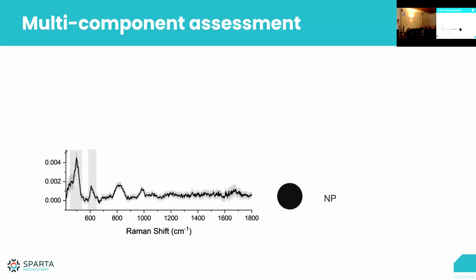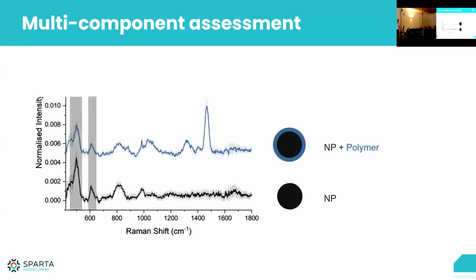So we have the bare nanoparticles, and you can see different marker peaks that we can draw down here. And then we're adding a polymer on the surface. And you can see we still have that same core composition, but a bunch of extra peaks come up from the polymer that we coated on the surface of these particles. And again, we could look at the variation in that polymer coating as well. This was super homogeneous, which you can see from this average plus the standard deviation in this little shaded area. Again, this is the standard deviation that comes from the variation within your population of particles, not just from repeat measurements of the same set.